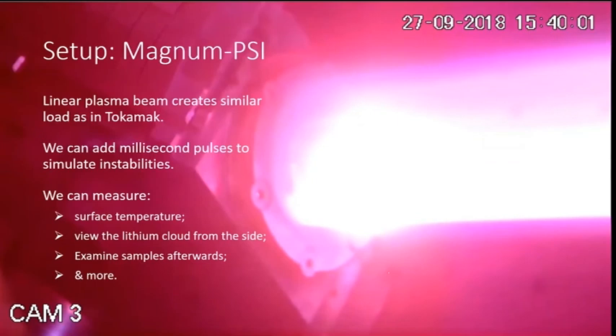We use Magnum PSI. You have seen it already in the movie in the beginning. It is a linear plasma beam that creates conditions very similar to a tokamak, actually. We can add millisecond pulses on top of a steady state load. So you can turn the plasma beam on for hours, but you can add millisecond pulses to mimic plasma instabilities on top of this. For those in the fusion field, of course, I refer to the ELMs. And then we can measure a lot of things, but today I'm going to take a look at surface temperature, a view from the lithium cloud that we can see from the side with a high-speed camera. And of course, we can examine the samples afterwards.